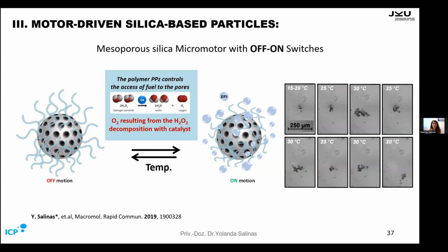So the first trial was to put the polymer around and see if we were able to control the switching on and off of the release of the bubbles. We used different types of catalyst inside the pores, and we were able to see the degradation of hydrogen peroxide, that is the chemical fuel, into water and oxygen bubbles. And this gas was able to be controlled on and off by changing the temperature, as we can see here. Between 15 to 20 degrees, we saw almost no bubbles. At 25 degrees, the bubbles start forming. Then at 30 degrees, more bubbles. And when we decrease the temperature, this stops. We could switch on and switch off several times, which was very interesting.